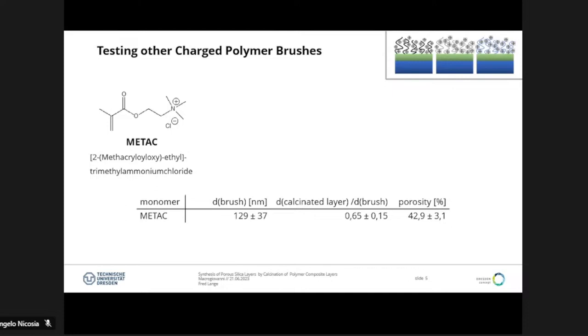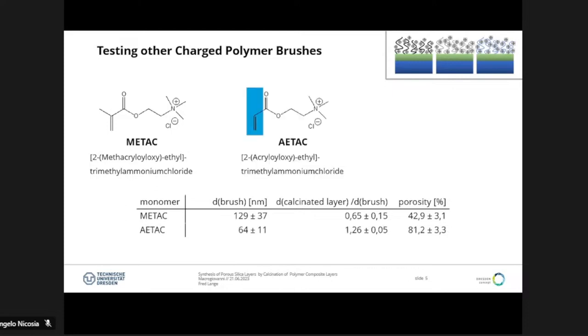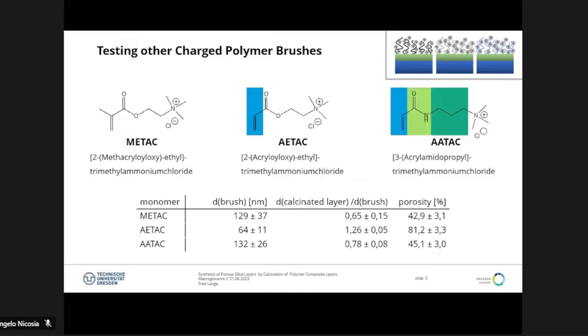In the next step, I then changed to an acrylate and also used an acrylamide. And I was able to show that even by just changing the polymer, the parameters of the achieved porous silica layer differ a lot.